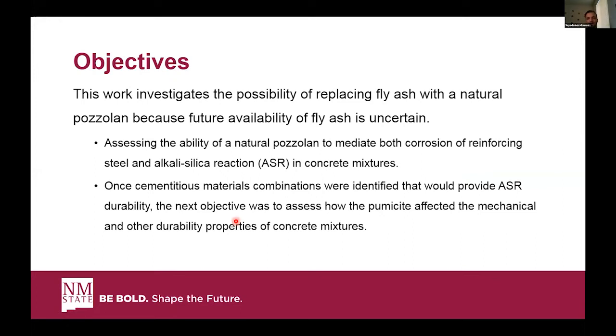The main goal of this project was to evaluate the ability of pumicite, this natural pozzolan, to replace fly ash, because we all know that the future production and availability of the fly ash is uncertain. In order to do so, first, we perform some ASR tests and corrosion tests to see how much natural pozzolan we need to mitigate the ASR. And then in the next part of the project, for the promising mixtures, the mixtures that were acceptable in terms of ASR, we perform some mechanical tests and other durability tests like RCPT, shrinkage, surface resistivity, and freezing and thawing tests.